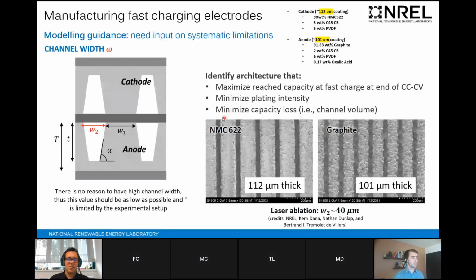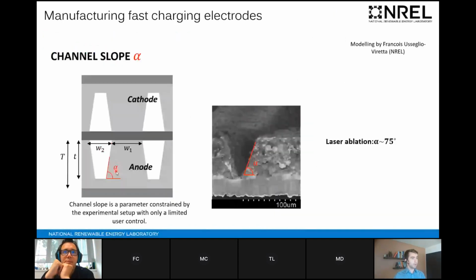So we have to first characterize what the laser is capable of. Some of the important parameters to restrict the range the model explores include the width of the channel, the pitch of the channels, W2 and W1, and alpha, the angle of the channels. Can we control the thickness of the channels, so T here as well? Through characterization, we found that W2 for the laser system that we use is limited to about 40 micrometers, so we constrain the model to a W2 of about 40 micrometers. The alpha is about 75 degrees, and we constrain the model again to about 75 degrees.